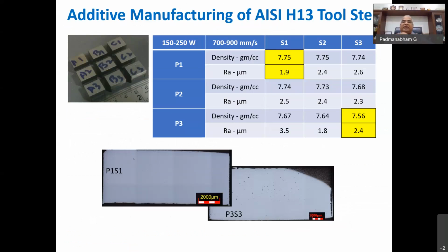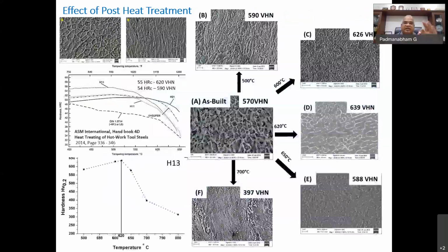So different power and scan speed combinations. You can see the density achieved as well as the surface finish achieved. Selected parameters in terms of scanning speed and power have been used. And these are the microstructure of the selected one. And a simple post heat treatment of about 620 degrees centigrade. You can see the structure changing. You see the diagram D.